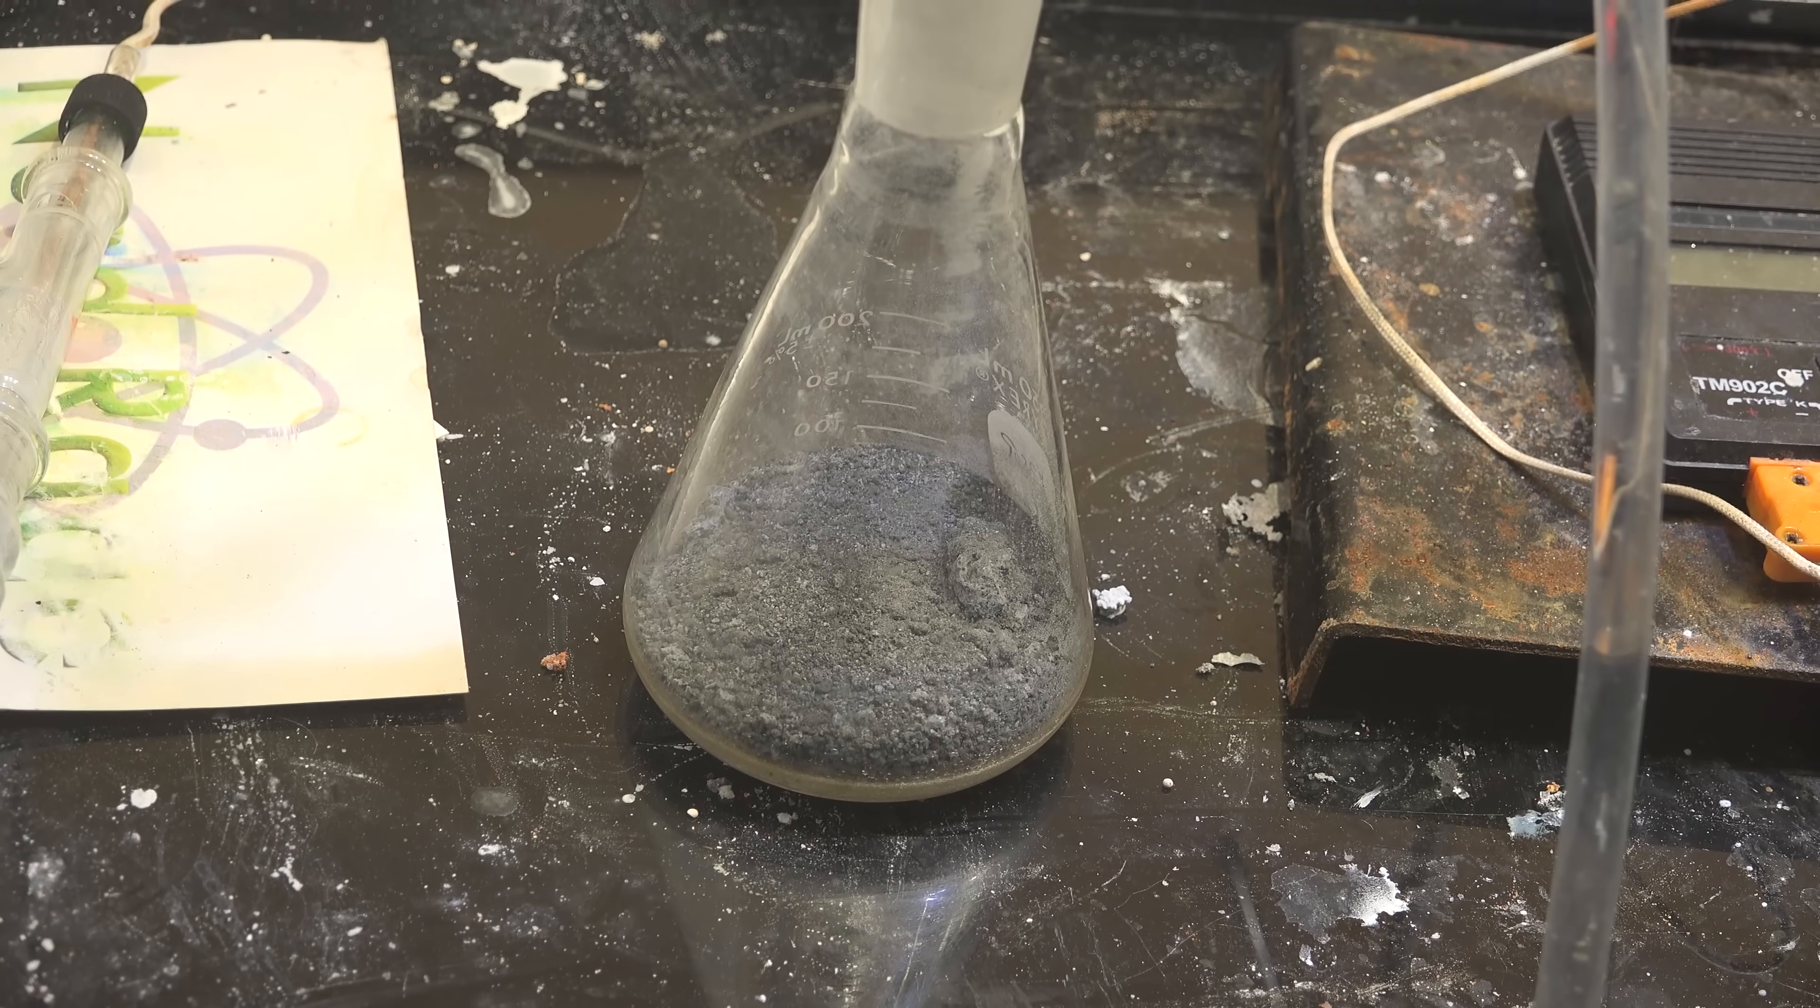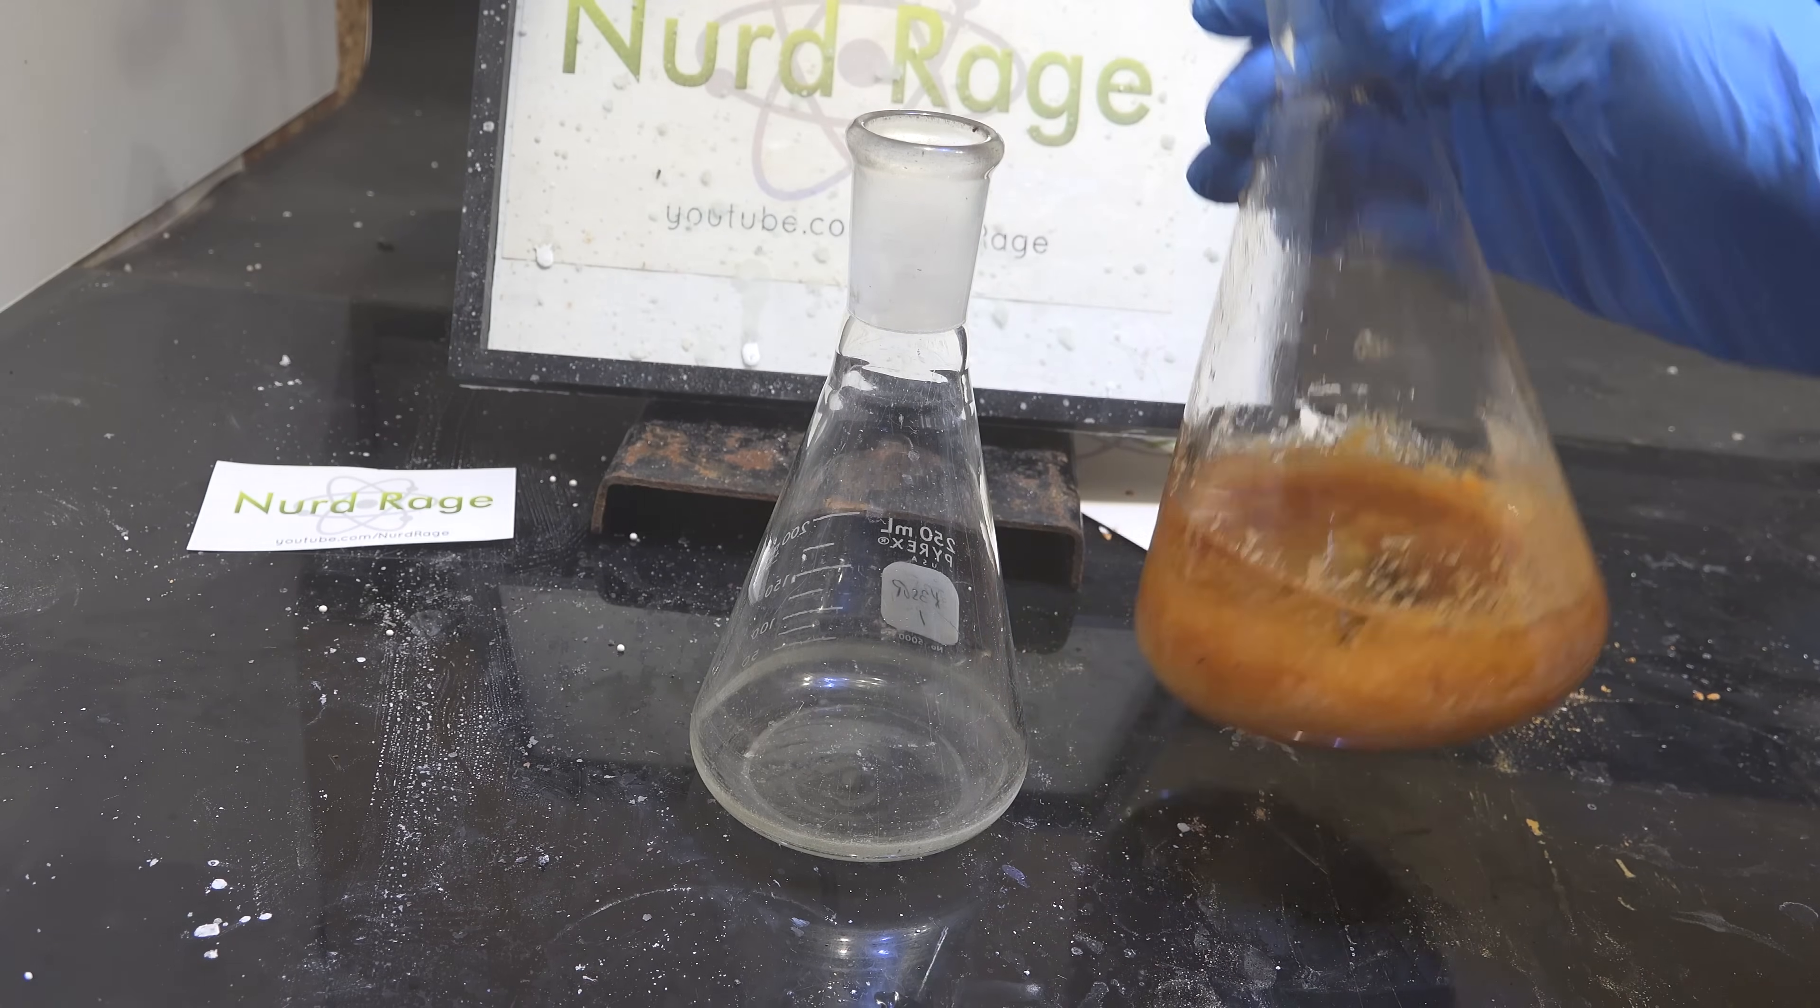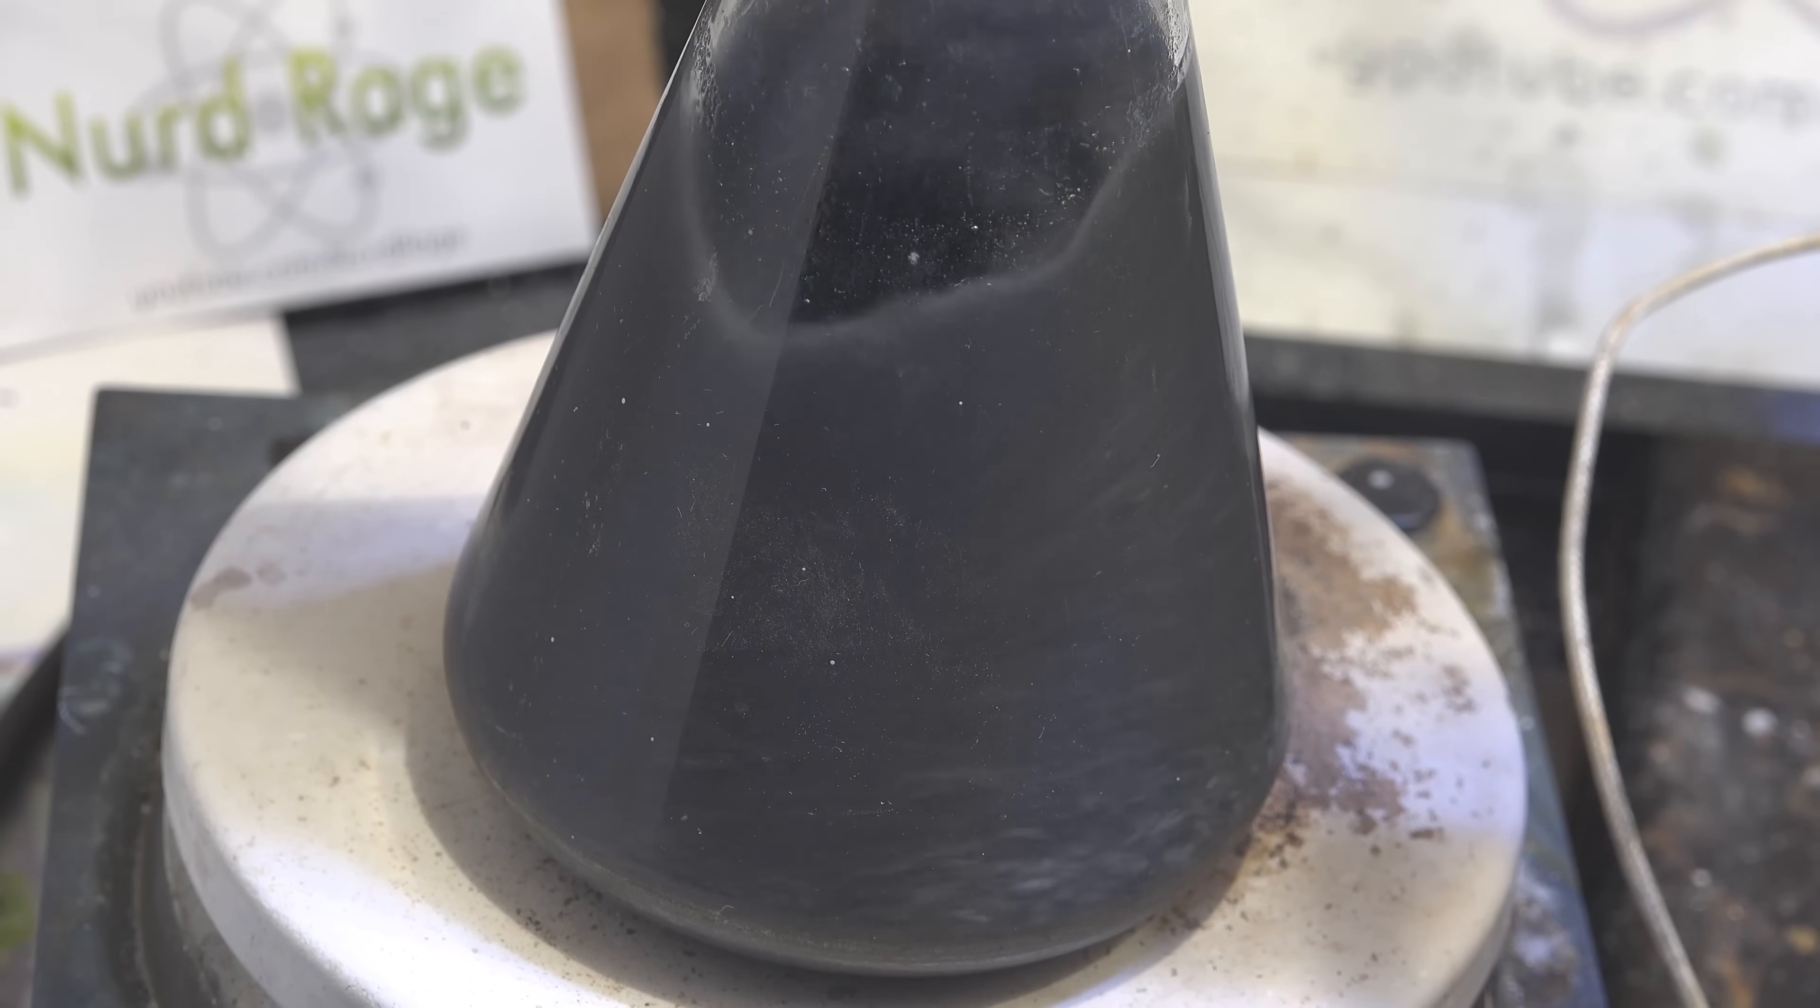And here it is after being poured into an Erlenmeyer flask. Now for the secret ingredient, add about two to three times its volume of 1,4-dioxane which I showed how to make in a previous video. I'm using purified dioxane but you can use dioxane that was dried over sodium hydroxide. The amount of moisture and contaminants will decrease yields slightly but the process will still work. Now drop in a stir bar and set up a distillation apparatus around the flask. Turn on the stirring, the cooling water and the heating and distill off the dioxane.